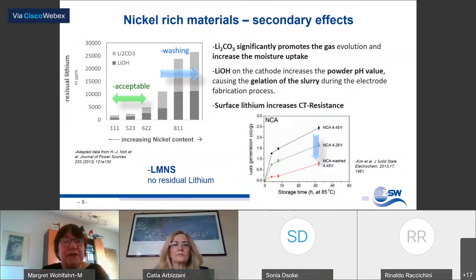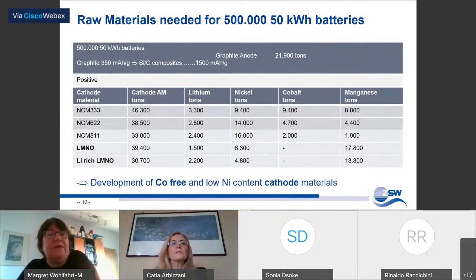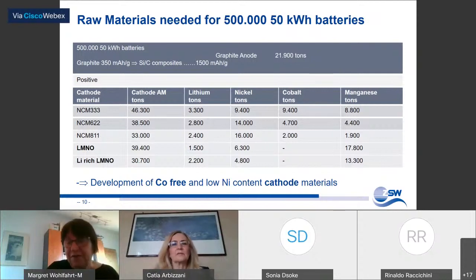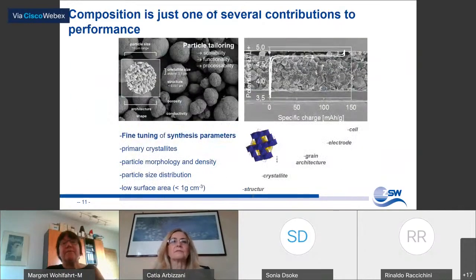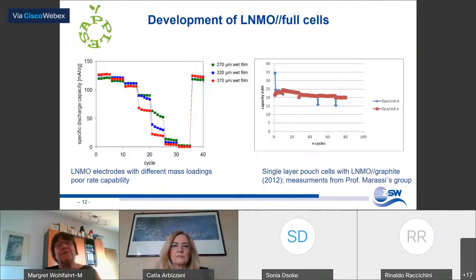There's another material, this high voltage lithium manganese nickel spinel, which has no residual lithium. And if we look at the demand for raw materials, high voltage spinel is a very attractive material, for it's not only cobalt free, it also has a low nickel content, and it's possible to add an additional lithium into the structure. Also here, the composition of the material is just one of several contributions to the performance. Also here, optimizing primary crystallites, particle morphology, particle size distribution is very important. Also to have a very low surface area to avoid side reactions with the electrolyte.